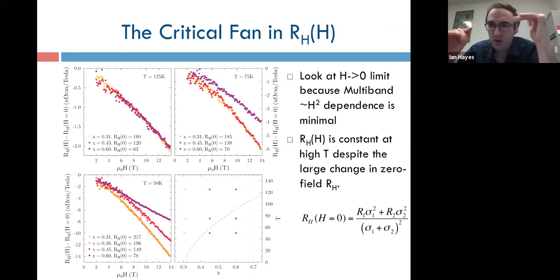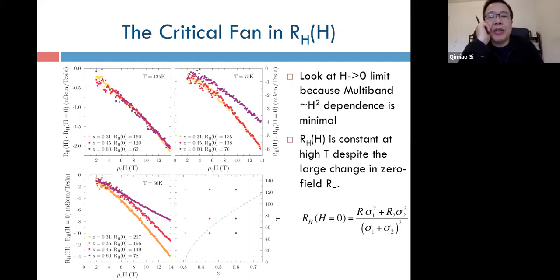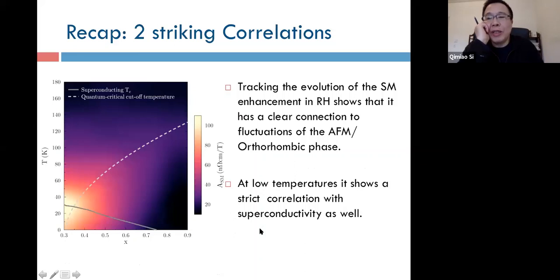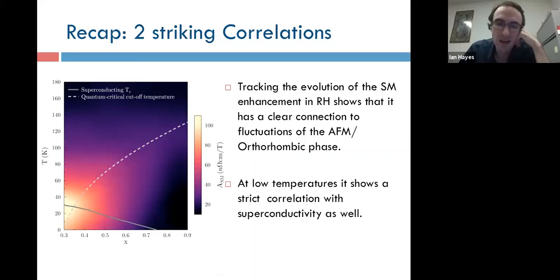Yeah, so a question of how quick the transition is between, say, the totally normal Hall coefficient on the overdoped side and the optimally doped or underdoped behavior. Yeah, because you refer to the strange metal component of the Hall, and one could perhaps look at that. It's a good question. Looking at it in detail will be a little tricky because of the limits of high field measurement. Broadly, as a function of temperature, it sharpens a bit. Just looking at the color plot here, you can tell that there's a broader region of enhancement at intermediate temperatures, and it sharpens up as you go towards lower temperatures.